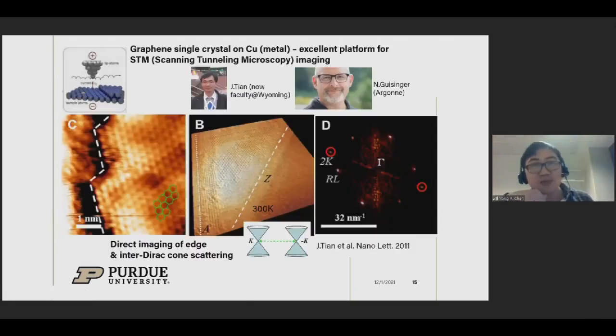Here's one example. This type of experiment, which is an STM experiment, would be difficult if you put the graphene on, say, silicon oxide or an insulating substrate. So our CVD graphene on metal, in this case the growth substrate copper, provides a very good, convenient setup for this kind of experiment. With scanning tunneling microscopy, this is work done by my former postdoc Ji Tian in collaboration with Nathan Guisinger, a scientist at Argonne National Lab, using the STM they have at Argonne. So we traveled there to do the experiment.